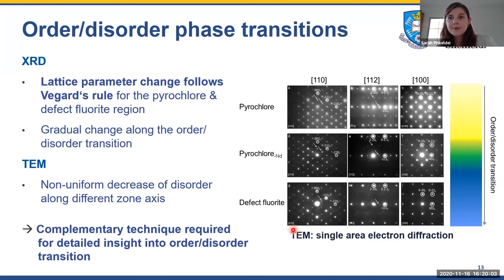But when we looked in depth with transmission electron microscopy, you can see here some patterns for a stoichiometric pyrochlore, which is a neodymium zirconium pyrochlore, Nd2Zr2O7. And then you can see this is the pattern for a pyrochlore structure where part of the neodymium has been replaced with zirconium, so with a B-site cation. And in this sample, so much of the neodymium was replaced by zirconium that we actually ended up with a disordered structure, a defect fluorite structure.